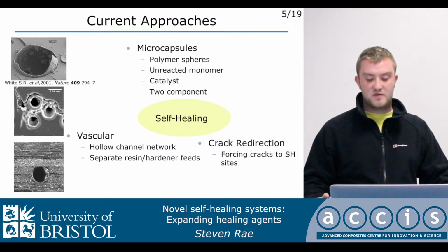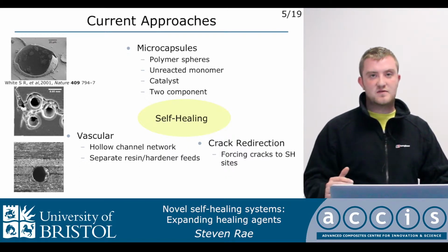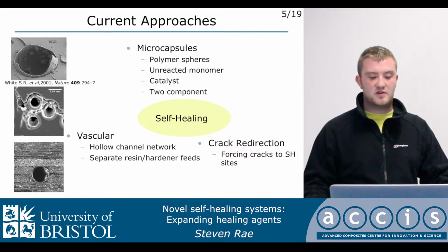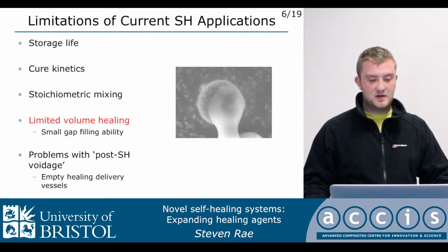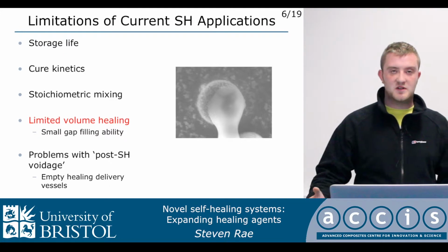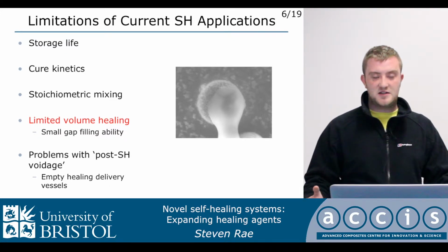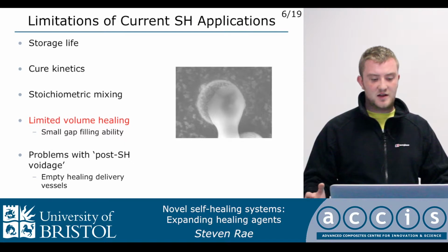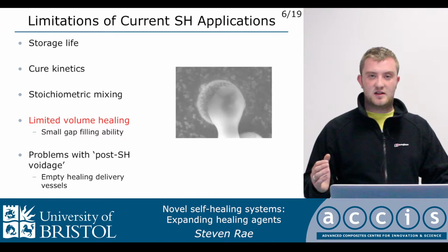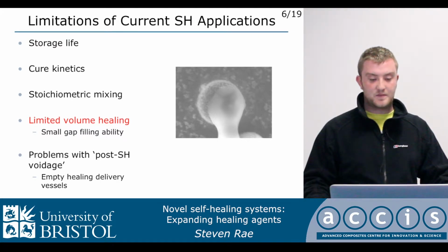The other area of research we perform at Bristol is crack redirection, so we can force the cracks to drive them towards an area of self-healing to ensure that they are healed. But these systems come with their own limitations, namely storage life, cure kinetics, and achieving stoichiometric mixing. And importantly, they'll have a limited volume of healing, especially with microcapsules. And also we have a problem with, after the impact event and the healing agent has been delivered, we're left with the voidage of empty microcapsules or vascules.